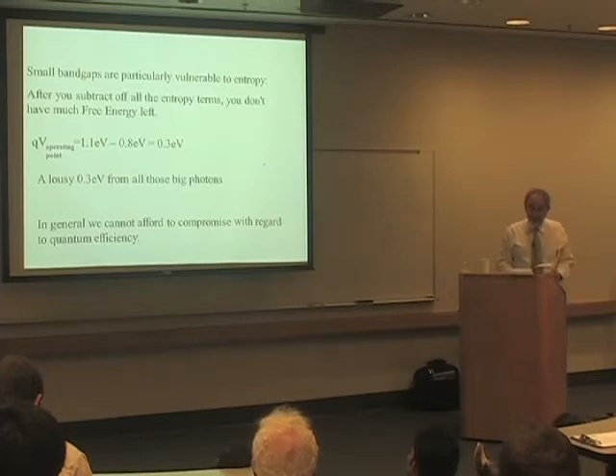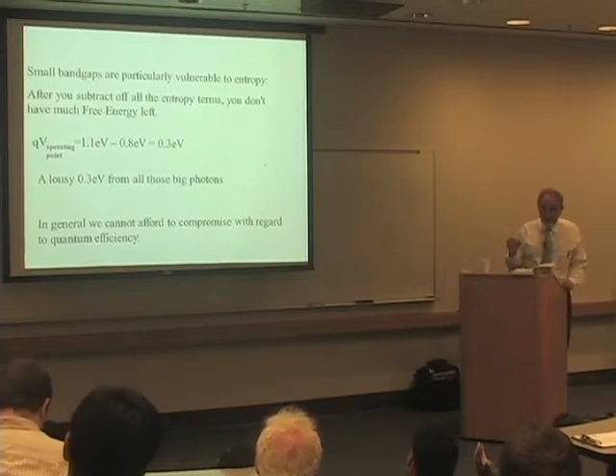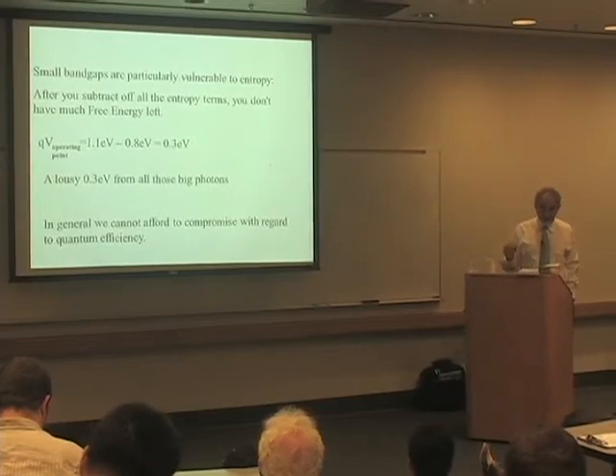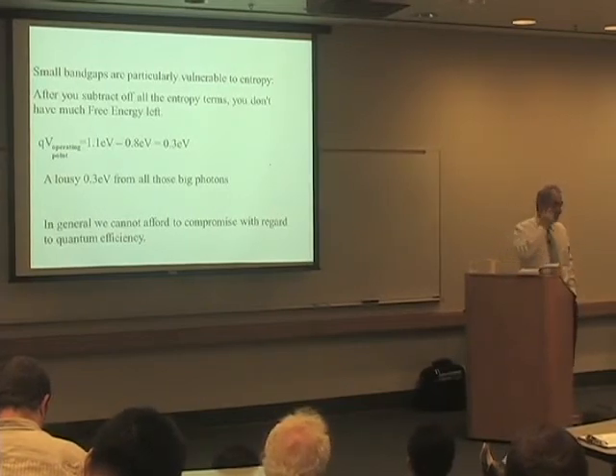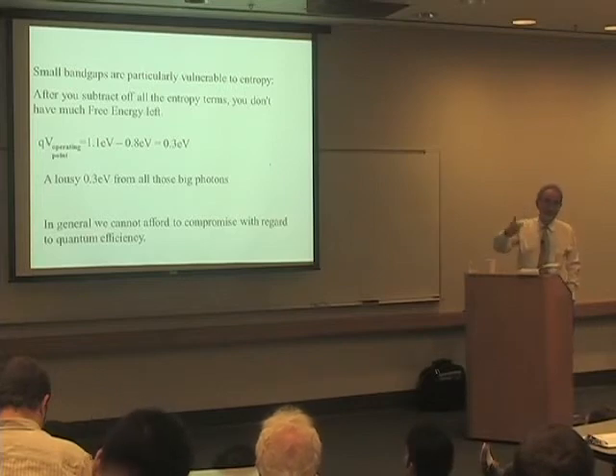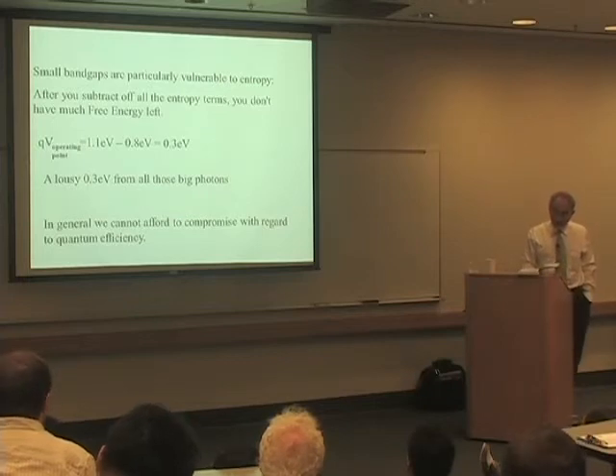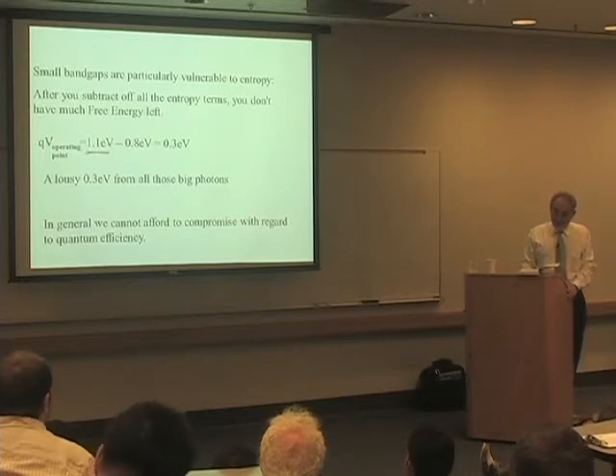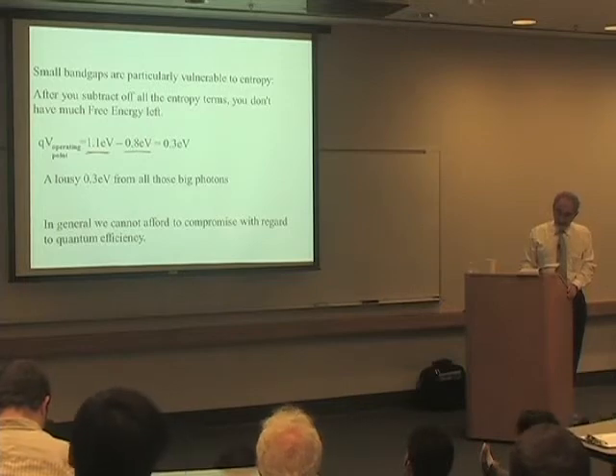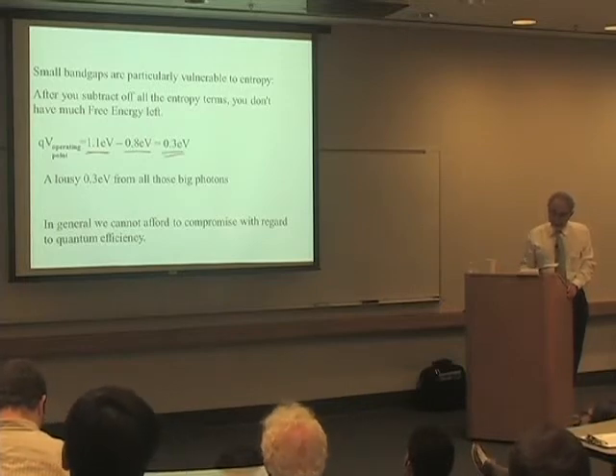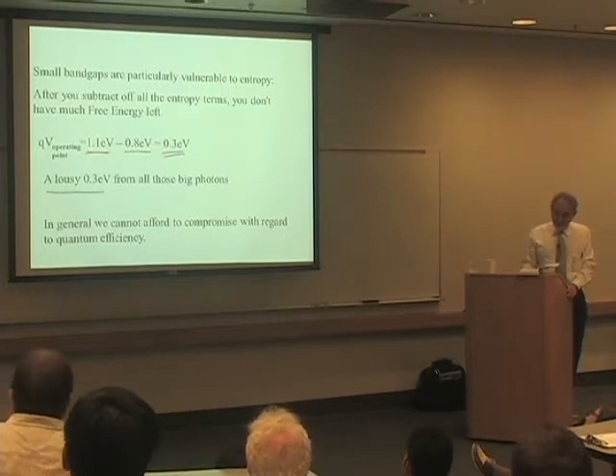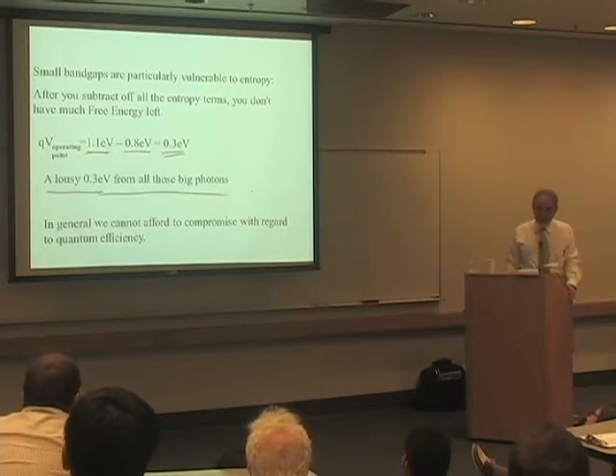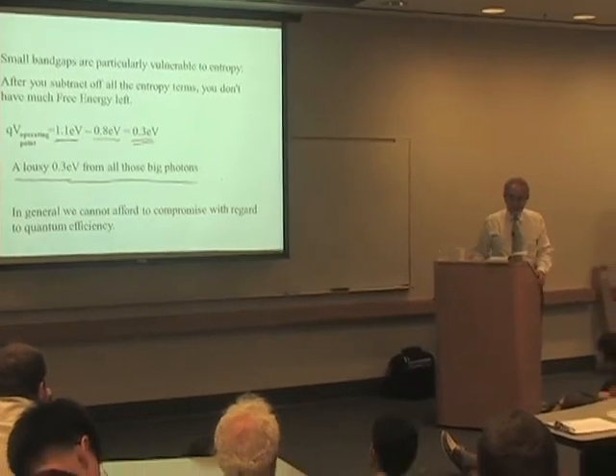But there's something very important we learned from this. When I got into solar cells, I went to the experts and I asked them, how do I know what voltage to expect on the solar cell? And they said, please expect two-thirds of the band gap. Now, that's wrong. It is the band gap minus a certain amount. So let's say you're at silicon. You have a band gap of 1.1 eV. And if you add up all those entropy terms that I gave you, oh my god, you're down 8 tenths of a volt. And so out of all those big photons, you end up correcting for all the entropies and you end up with only a lousy 3 tenths of a volt at the operating point.